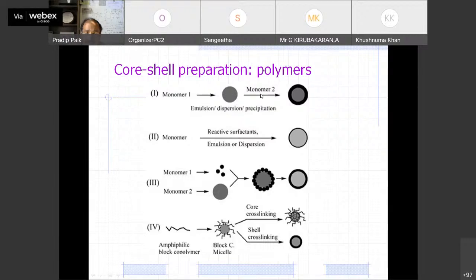Okay, you take a second type, monomer 2, which you have to polymerize. So polymer will be there inside the core and polymer will be there inside the shell. But you have to choose in such a way that there will be an affinity or electrostatic interaction between monomer 1 and monomer 2. Even if monomer 1 produces these particles, there should at least be an interaction force or affinity with the monomer, so that the monomer can deposit on the surface and then create the shell.